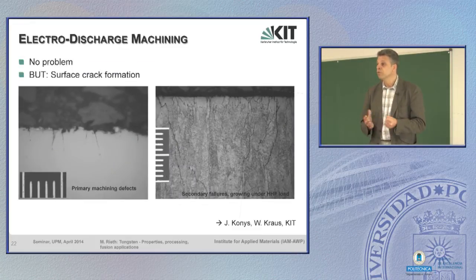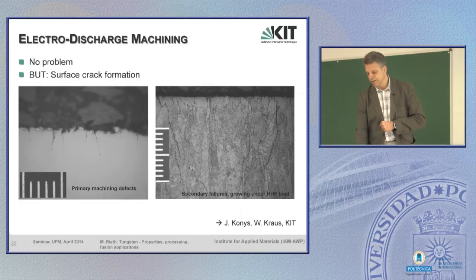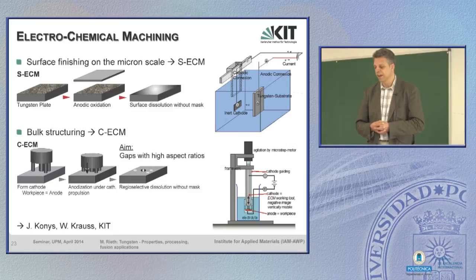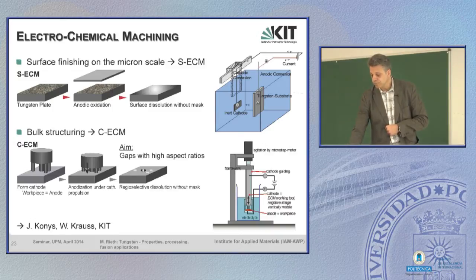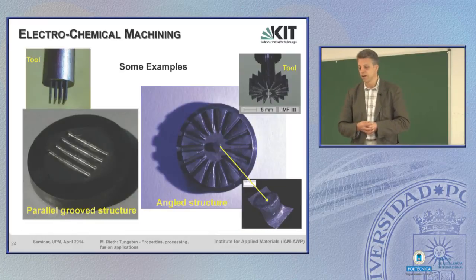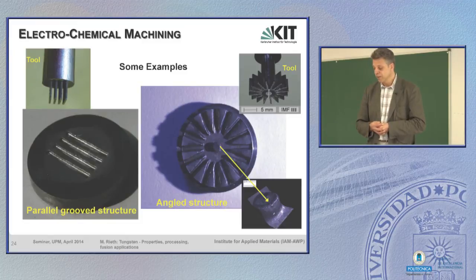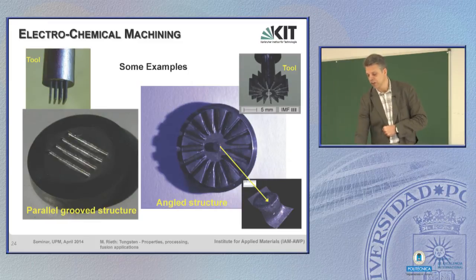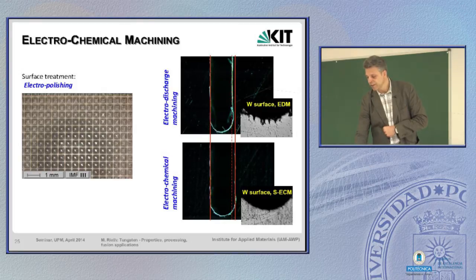Electro-discharge machining is also no problem, can be easily done. But as you can see here, this induces many and quite deep surface fractures. So another type of machining, electrochemical machining, has been invented. I don't want to go into details here. It's a typical electrochemical fabrication process. Here we can shape and vary the surface of tungsten by different tools. Here are just a few examples. But the main advantage here is that it doesn't induce these cracks as in electro-discharge machining. You see it here. This is after EDM, after discharge machining, and here the surface by electrochemical machining, which is without cracks or almost without cracks.